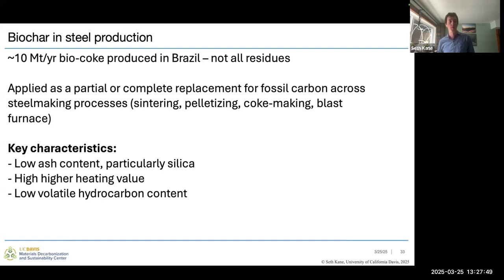The key performance characteristics are going to be that for coke in the blast furnace itself, you need fairly high mechanical strength to support the iron ore on top of that coke, because you flow the air up through the coke to produce the reducing gas. You need fairly low ash content, and particularly silica. If you have additional silica, you then need to add additional lime into your process to form slag from that. And that's going to be associated with additional greenhouse gas emissions.